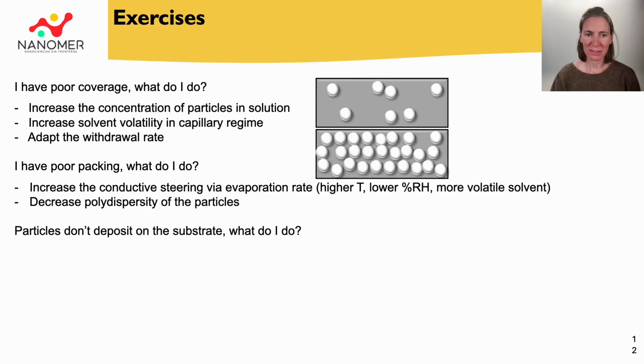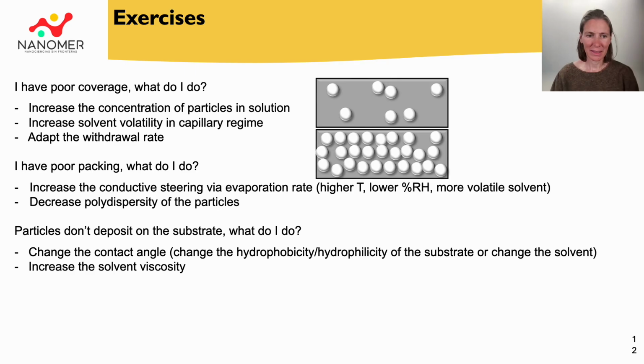Let's say your particles don't deposit on the substrate. What can I do? You can change the contact angle, making your substrate either more hydrophobic or more hydrophilic. Or you can increase the viscosity of your solvent and work in the faster withdrawal speed regime.